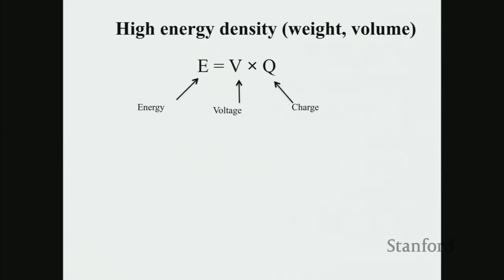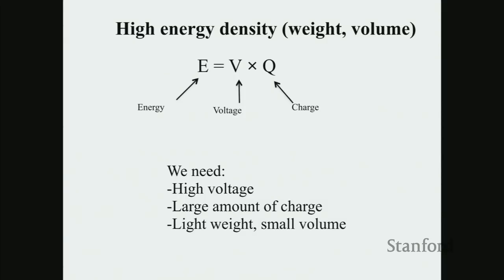So it comes back to the very simple equation to look for a new chemistry. The energy equals voltage multiplied by charge. You need to either increase the voltage or increase the amount of charge you store. And the voltage has a limit. You see the current lithium-ion battery allows you to sit at about 4 volts. 4.1, 4.2, 4.3, once you hit 4.5, the electrolyte is really not that stable, not to mention 5 volts. The voltage is too high and decomposes your electrolyte. So there's a limit right there. And the amount of charge you can store, you have a lot of room to play with. So eventually you want to store this charge with that voltage holding right there using lightweight and small volume.